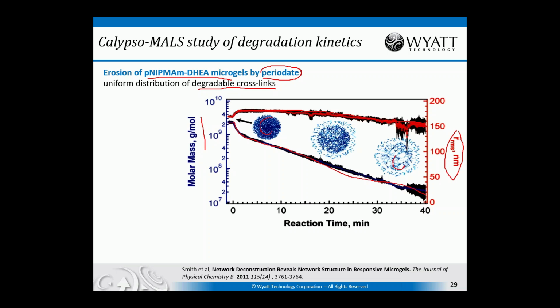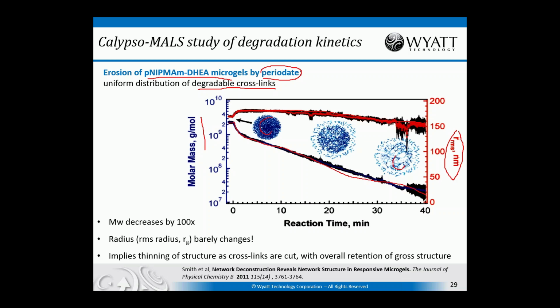And the interpretation is as illustrated here. It shows us that even though we're breaking the crosslinks and reducing the overall molecular weight of the polymers, they're not breaking up. They're kind of sticking together. And the overall core structure of the particle is retained, even though the internal structure is being degraded. So we have approximately a two order of magnitude decrease in molecular weight, but very little change in the root mean square radius. So there's a thinning of the structure as the crosslinks are cut, but the gross structure is retained overall.